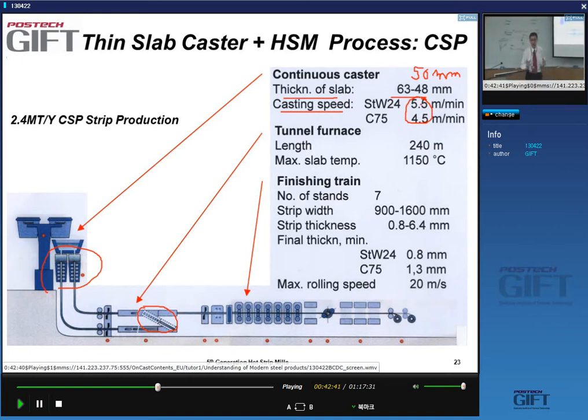It's not much different than the casting speed in a continuous caster for slabs, but in a continuous caster you cast a lot more volume, right? And so one of the solutions to improving productivity for this technology is to increase the casting speed. Yes, and that's not an easy task. But in general, you'll see people casting at 4, 5, 6 meters per minute, yes?